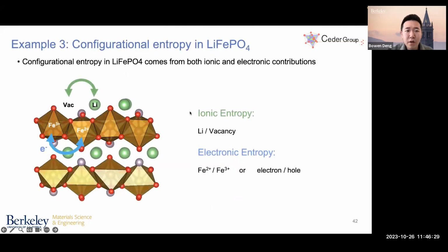So in the third example, we apply CHGNet to solve the configurational entropy in lithium iron phosphate. The configurational entropy in lithium iron phosphate comes from both ionic entropy and electronic entropy. Specifically, the ionic entropy arises from the lithium vacancy interchange, and the electronic entropy arises from the interchange of the iron 2+ and iron 3+, and essentially the distribution of the electrons and holes.